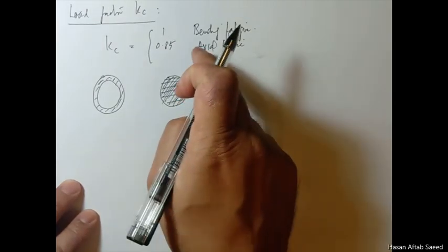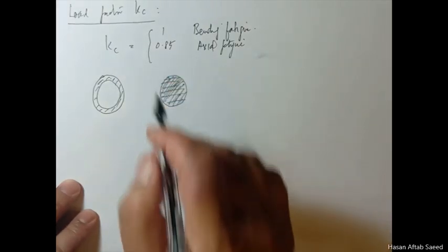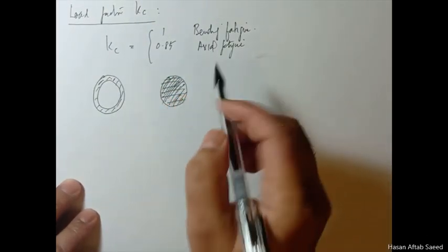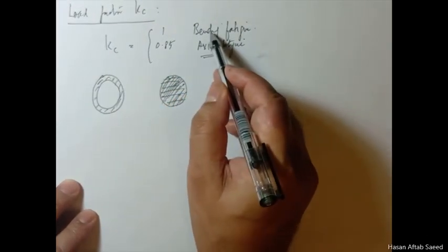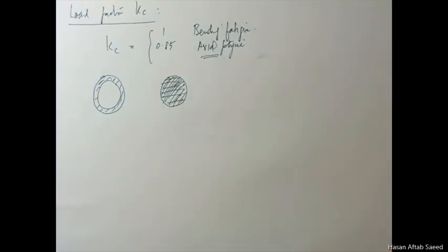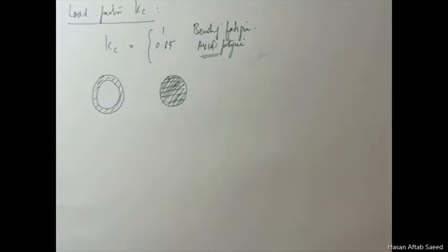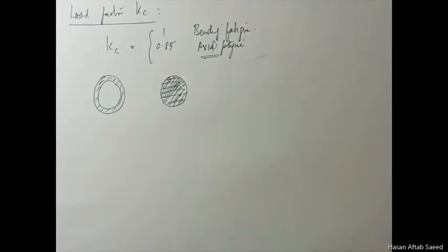In this respect, yes, but overall, no. There's no doubt that endurance limit will be reduced in this case as compared to this one. But there is also no doubt that it is very difficult to produce very high stresses by axial loading as compared to the bending load. Bending is the easiest way to apply loading because of the momentum that is involved.